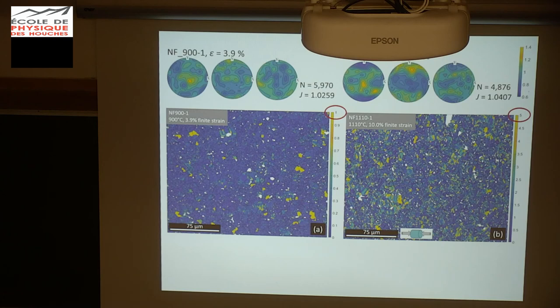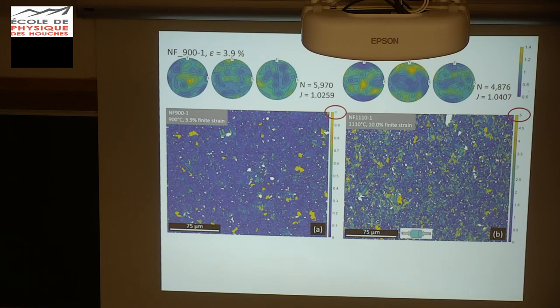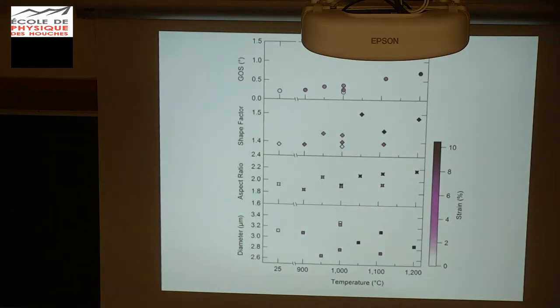For those who like CPO, we also tried to be overly positive. There is basically something that starts to look like something, but my postdoc put it the inverse way — the dark color is the lowest density, not the highest. And if you calculate the J-index, you go from one-point-something to one-point-something. We can dig out some features, but it's not that great. Still, we have those great deformation curves showing steady state, so something has to be happening in the samples.